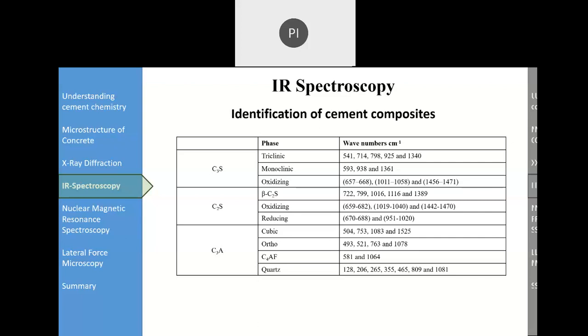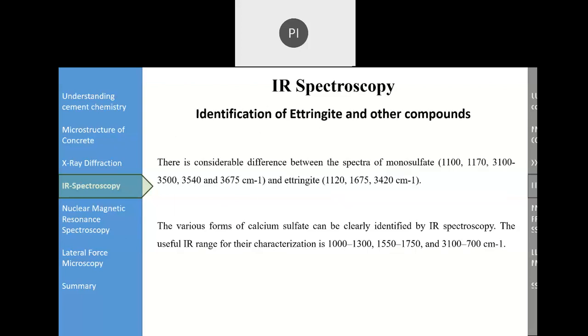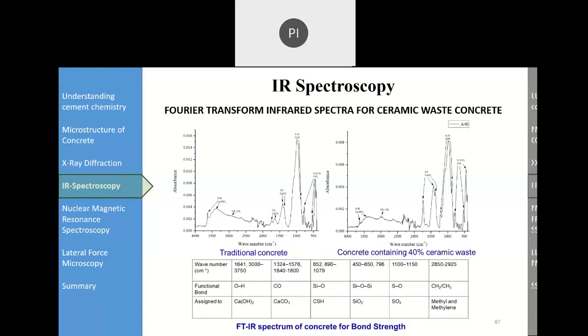Same is for C2S, in which form it is present, beta C2S, etc., then C3A in cubic or ortho form, or C4AF or quartz, whatever. So we have to identify these cement components, and we need to understand that there's a considerable difference between the spectra of monosulfate, ettringite, etc., and various forms of calcium sulfate can be clearly identified by IR spectroscopy. We can do FTIR also, through which we can obtain the functional bonds, find out to which mineral they are assigned, and that gives us the strength of concrete.